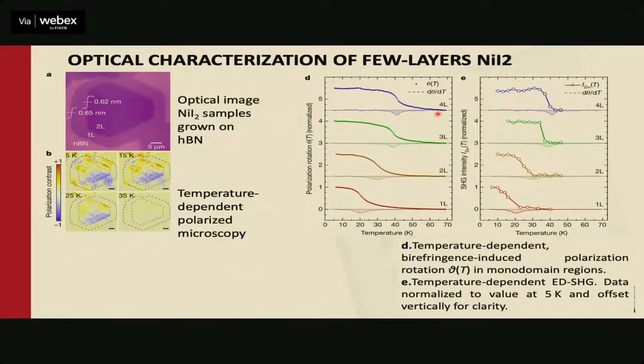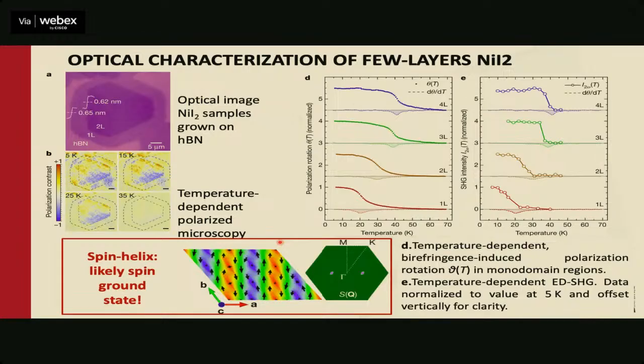From those results, they could tell us that there's a signal that emerges below a certain temperature. You see, this temperature is reduced if you go from 4 layers to 1 layer, but even at the monolayer level, you still have some kind of ordering developing. Additionally, they did a symmetry analysis, and they could tell us that there's a twofold axis. We have a triangular lattice, so we have a threefold symmetry, but they could tell us that there's a twofold axis. It means that the symmetry is reduced below the ordering temperature. And from this, we inferred that the twofold axis is consistent with the kind of spin helix that we predicted.